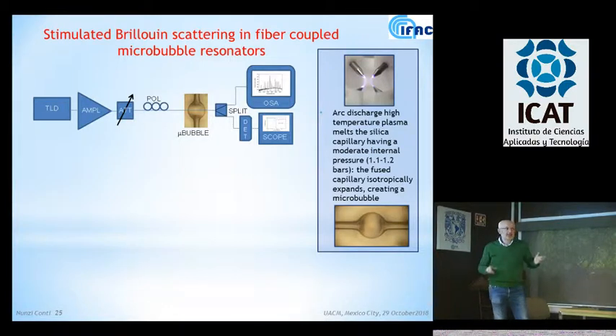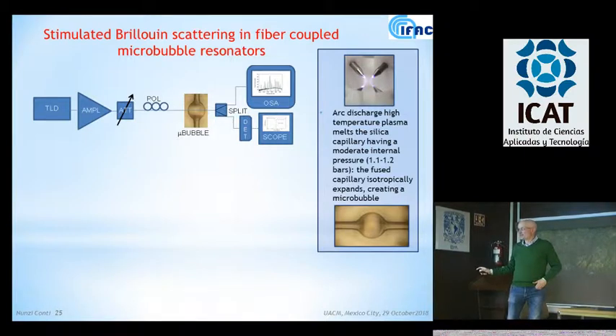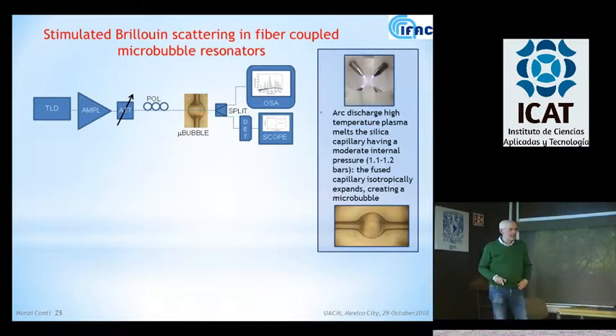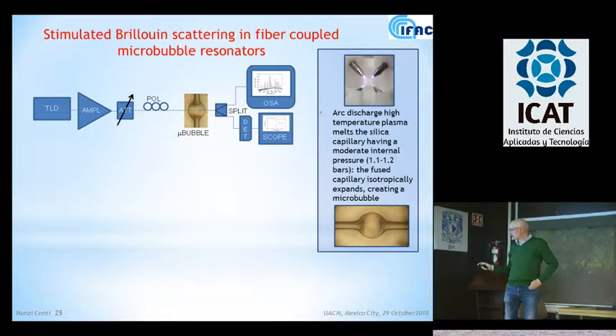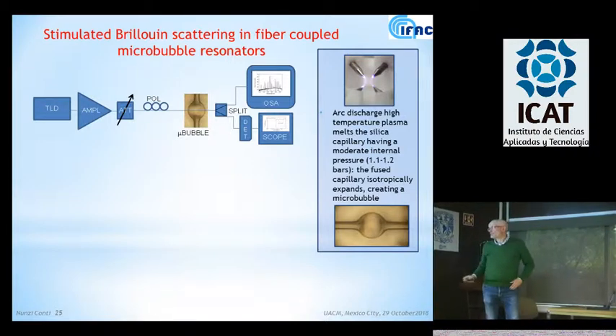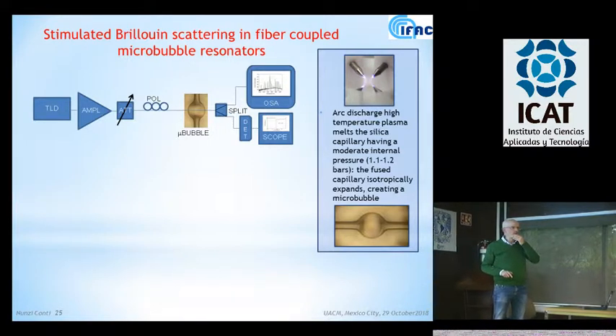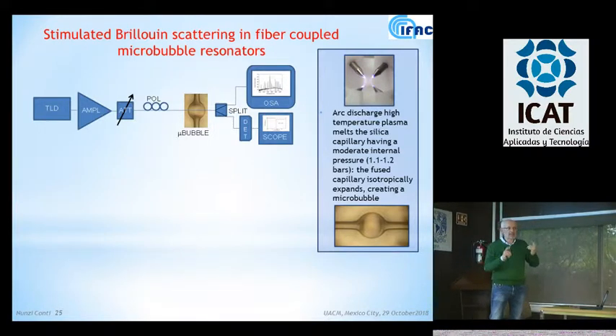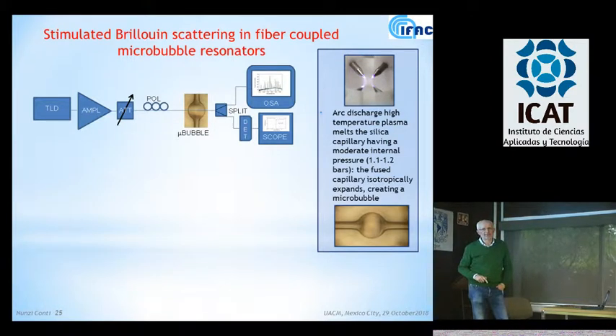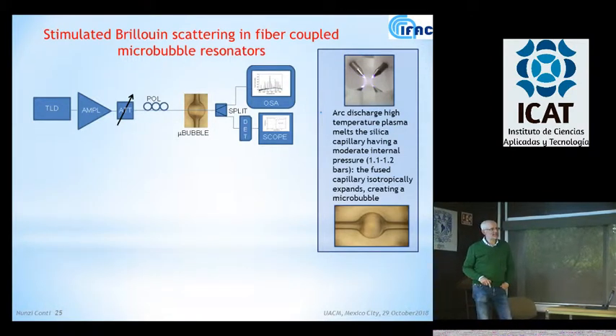Still, we do not always get the same result, especially in terms of the thickness of the wall, which is important. It's a multiple step process, not just one shot. We need to do it gradually while pressurizing it. So it's semi-artisanal. I would say even the polishing is the same, it's done in a quite homemade system.